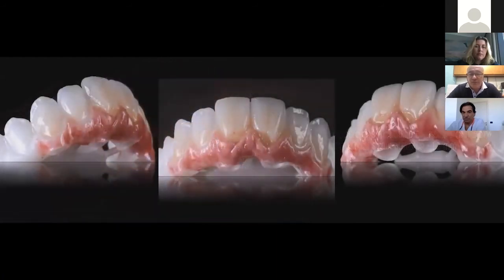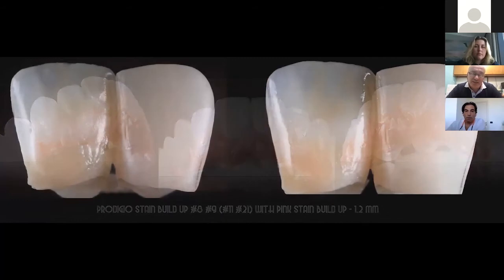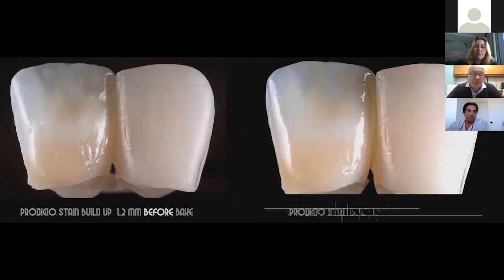If a technician feels more comfortable using the stain instead of the porcelain, the big advantage is that he can really see all the color he's placing on the framework. He can see and control all the texture. If you have a chance to use those materials, you will see the consistency is like composite. You can really control any anatomy you want. Here on the side, on zirconia, you can see we can build up to 1.2 millimeters. The color before you bake is very, very similar after you bake. So you can control transparency or mamelon effect, anything you wish to put on your tooth, before you bake it.